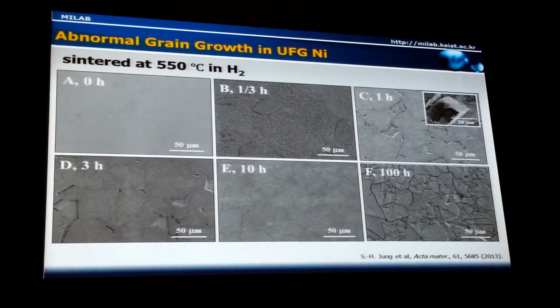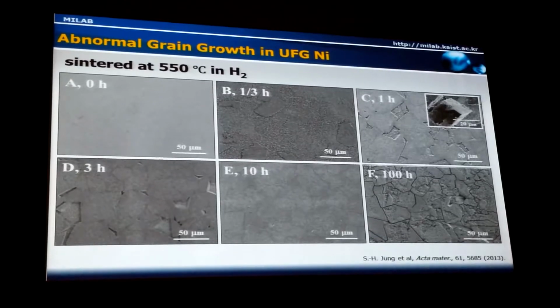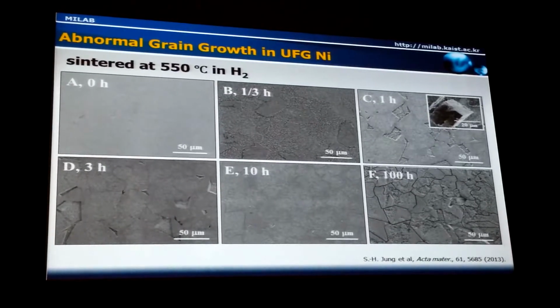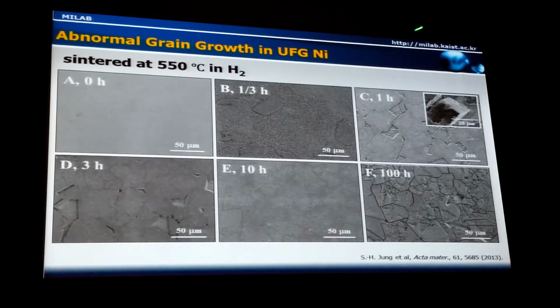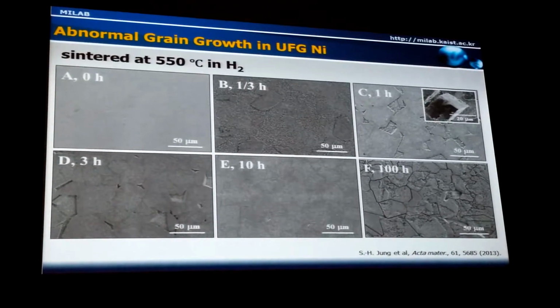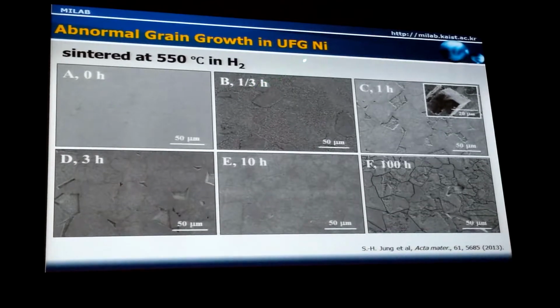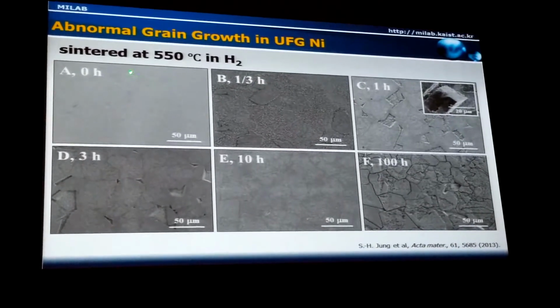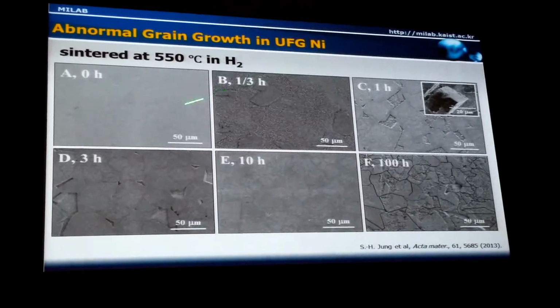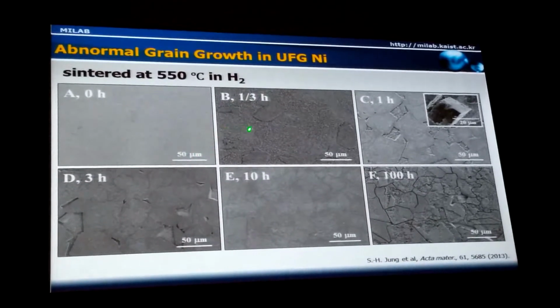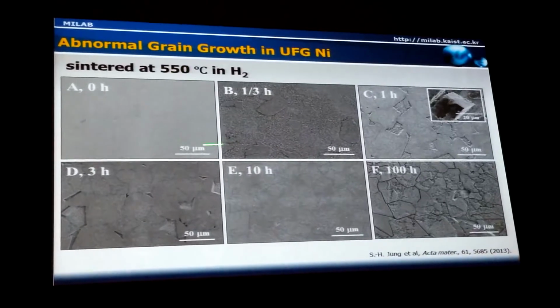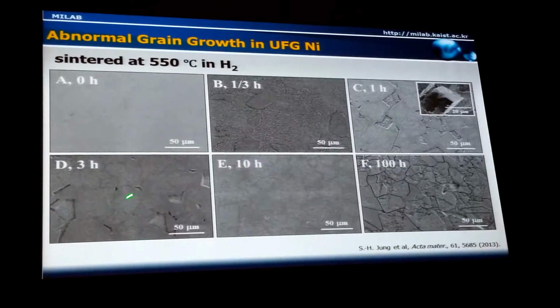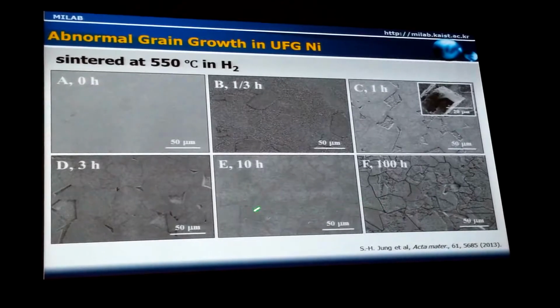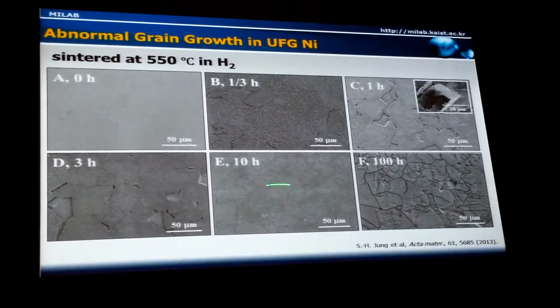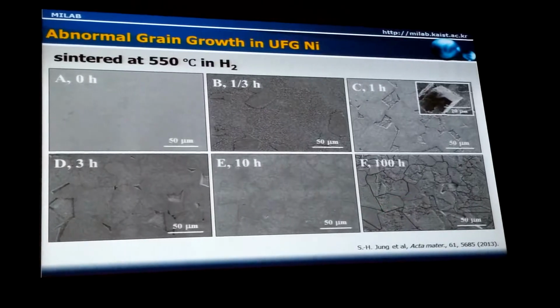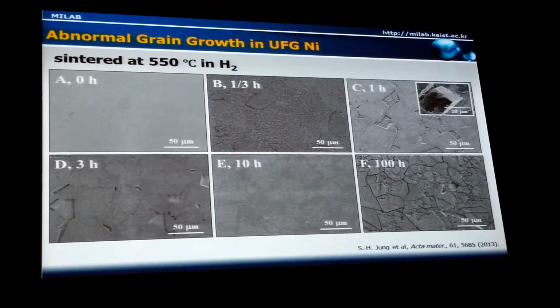Now, let me show the last example that exhibits different types of grain growth in the same sample. It's an ultrafine grain nickel, 180 nanometer. This is not a ceramic material, but 180 nanometer nickel powder. And then we sinter the powder compact of nickel. Here, abnormal grain growth occurred at 550 degrees C, and the abnormal grains impinged upon each other. After impingement, there is essentially no change in microstructure or grain size, as shown in these two figures.